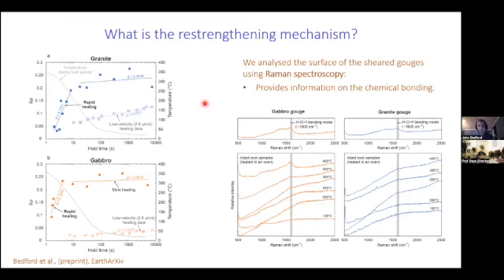So why have we got this change in the absorbed water? Well, what I think is happening is that how water reabsorbs on the surface of materials is very dependent on the structure of your material, of the substrate that it's absorbing onto. And if there's been some chemical change on that substrate during high velocity shear, which maybe then allows rapid bonding, then water can maybe reabsorb in a different mode once the gouge cools.